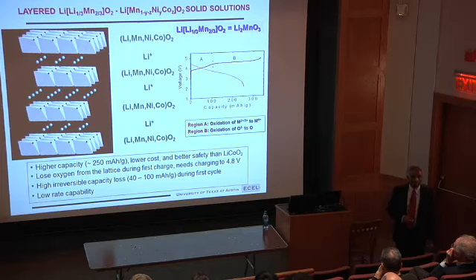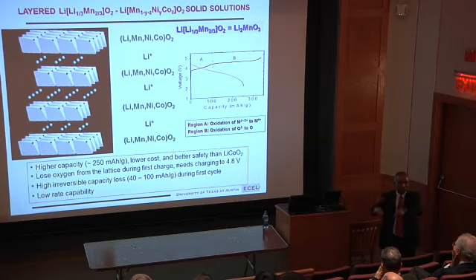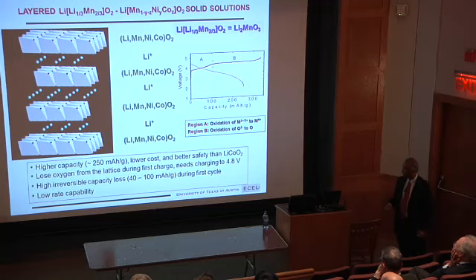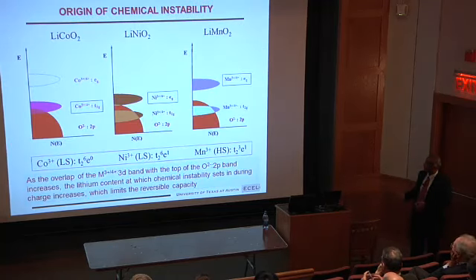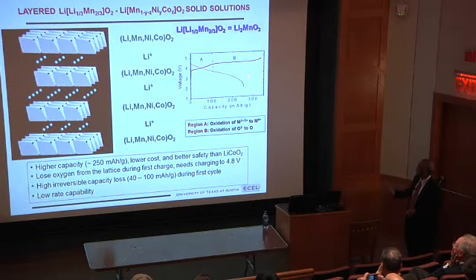So already the material surface is reacting with the electrolyte. And if it loses oxygen, you have a lot of oxygen defects, high surface energy. So the electrolyte reaction will be aggravated. So that's a problem. The surface has to be conditioned. And then the material rearranges after losing oxygen, having oxygen vacancies and rearranging. So that causes a difference between charge capacity and discharge capacity. Meaning, I pulled out a lot of lithium, but when I discharge it, when I use it, I can't put all of them in. So that's the problem.